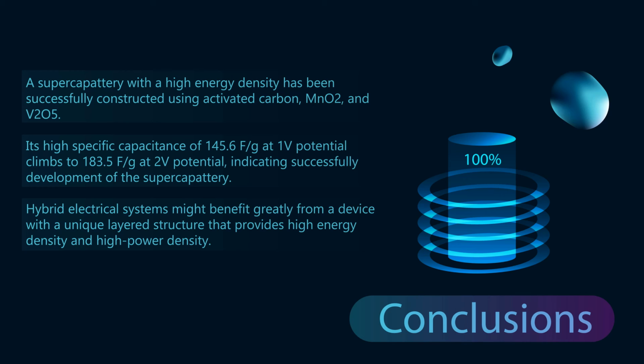The constructed supercapattery shows an ultra-high energy density of 101.9 watt-hour per kilogram, which is much higher than the energy density of a carbon-based supercapacitor of the same size. Thirdly, a hybrid electrical system might benefit greatly from a device with a unique layered structure that provides high energy density and power density at the same time.